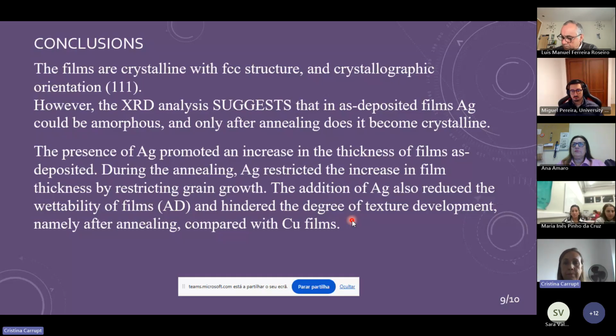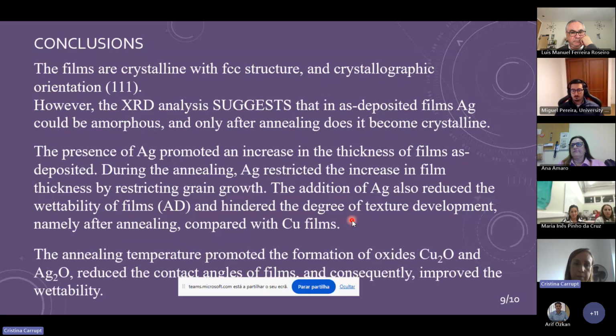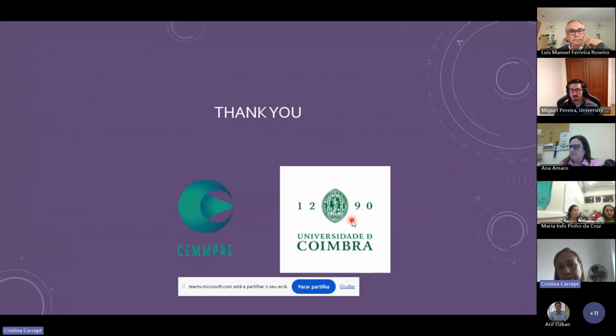to grain boundary. The addition of silver also reduces the wettability of film in the as-deposition condition and hinders the degree of texture development, namely after annealing, compared with copper film, because of the growth of the peaks 111 of silver. The annealing temperature promotes the formation of oxide, oxide of copper and oxide of silver, reduces the contact angles of films, and consequently improves the wettability. And that's all. Thank you for your attention.